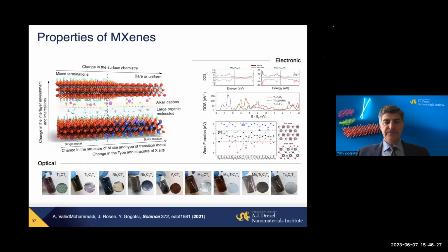All these properties are tunable initially by structure, number of layers, transition element, carbon, nitrogen, oxygen, mixing different elements in solid solution, surface termination, and intercalation of ions or molecules. And actually you can graft molecules on the surface of MXene. And again, unlike in graphene, you won't kill conductivity. You get OH on graphene, making graphene oxide, and conductivity goes down 6-7 orders of magnitude. MXene stays conductive.